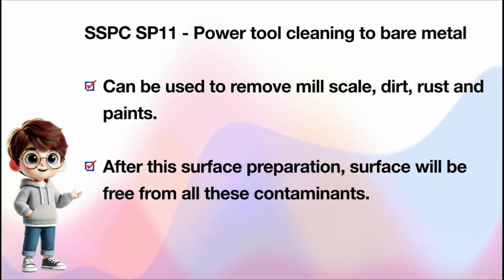Next, SSPC SP11, power tool cleaning to bare metal. It prepares a steel surface for painting by removing all visible contaminants and produces a specific surface profile. Before cleaning, the surface will typically be covered with contaminants like oil, grease, dirt, dust, mill scale, rust, paint and oxides. After SSPC SP11, the surface should be bare metal, free from all those contaminants. In the same way, a surface profile of 25.4 microns will be eroded during this surface preparation.